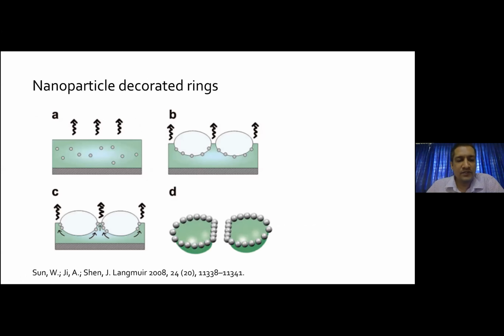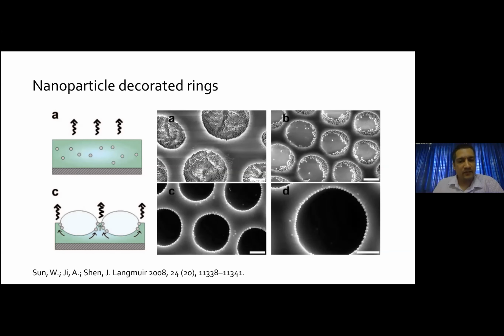Another approach, by Shen and group, is to allow nanoparticles to form decorated rings. If you see, these are silica nanoparticles that take the positions of the ring, and the silica particles are fluorescent labeled. The particles are of very small dimensions compared to the dimensions of the pore, and they are chosen in such a way that the concentrations are low enough to occupy only the rings and avoid the other places.